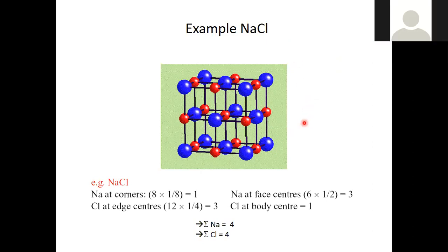It's FCC. Yes, that is correct. And why is it FCC? That is because when we have FCC, then translational symmetry with regard to FCC must hold. So that means that any point which is on the corner, which defines the lattice point, must be shiftable to the center of the face. Okay, so that's of course only possible if the atom which is at the center of the face is the same as the atom at the corner.